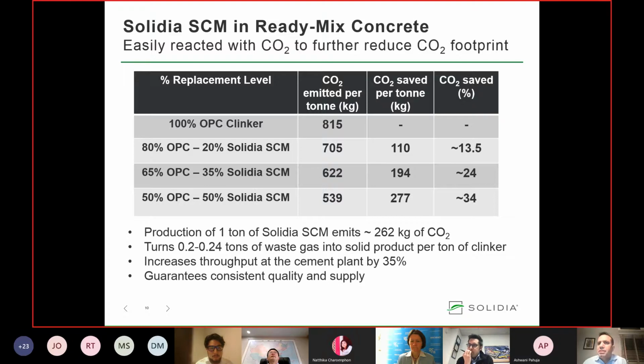When we produce 1 ton of Solidia cement, we are going to emit about 262 kgs of CO2. And what we are doing is turning 200 to 240 kgs of waste CO2 gas into a valuable solid product. So if I have 1 ton of clinker, at the end of this carbonation I'm going to have 1.2 to 1.25 tons of product. This also increases the throughput at the cement plant by about 35% compared to OPC clinker. So at a given time, you can produce 35% more material with this approach.